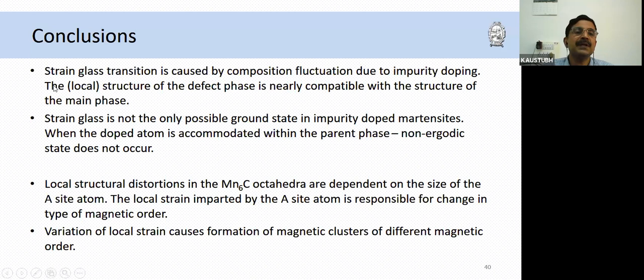In the first example, we said the strain glass transition is caused by composition fluctuation, and the defect phase, the local structure, is nearly compatible with the structure of the main phase. And strain glass is not the only possible ground state in impurity-doped martensite. It could be either a ferromagnet or it could be strain glass, at least in the Heusler alloys, and we need to understand this a little bit more.